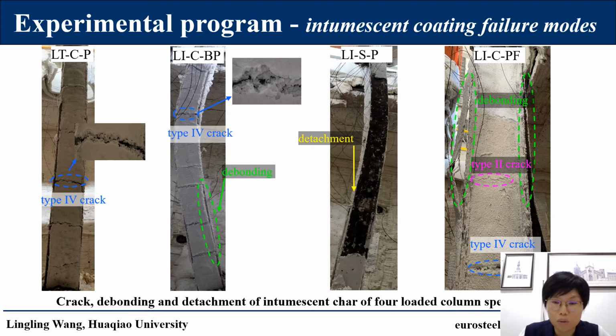It is important to determine the fire test days at which detachment appears. If it happens during the shortening stage, when the column is approaching failure, such detachment would not have a significant adverse effect. But if it occurs during the elongation stage, such serious failure would greatly affect the fire-resistant steel column. This will be examined by analyzing average temperature and temperature distributions in steel sections.